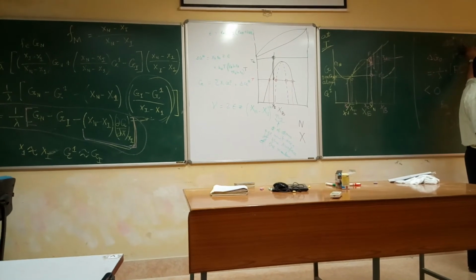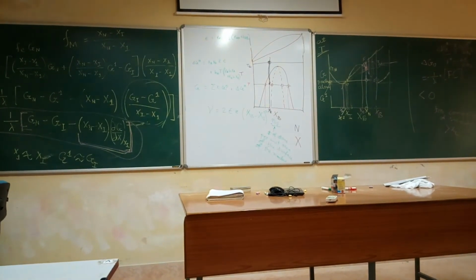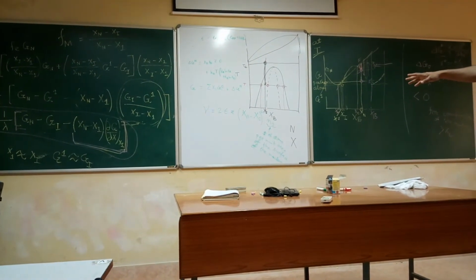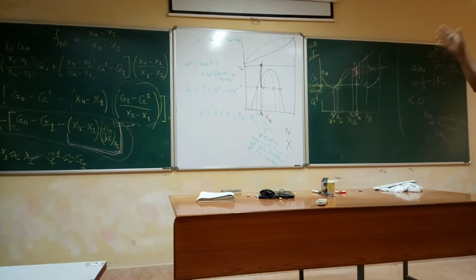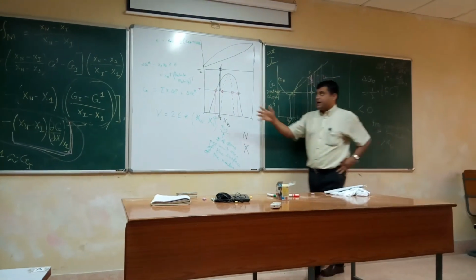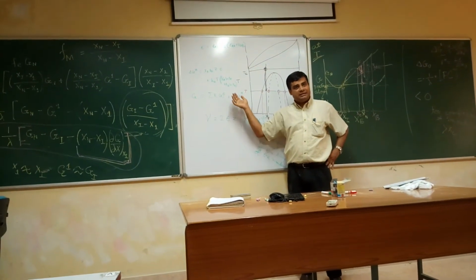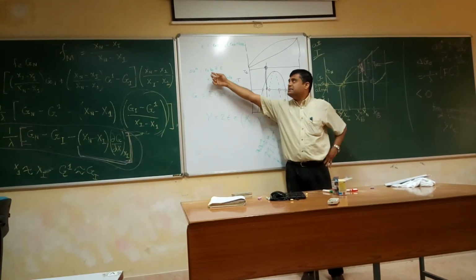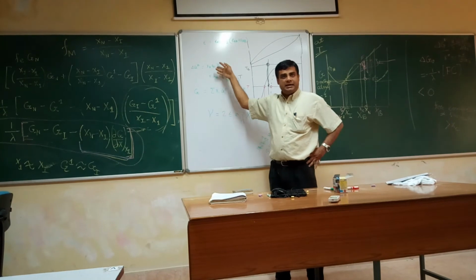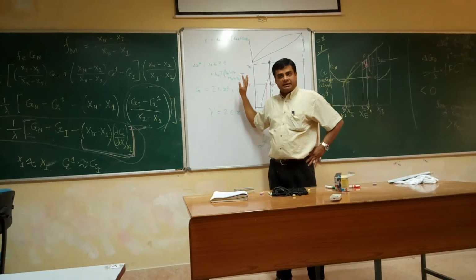Now delta G star contains delta GV and gamma, which are composition dependent, and that gives me an energy equation dependent on composition. Delta GV can be found from that equation, in which Gibbs free energy terms are there for different compositions, the alloy composition and the embryo composition, which can be obtained from the regular solution equation G equal to summation xi gi naught plus delta G mixing. Delta G mixing term is that excess term xa xb epsilon z plus kT summation xi ln xi.